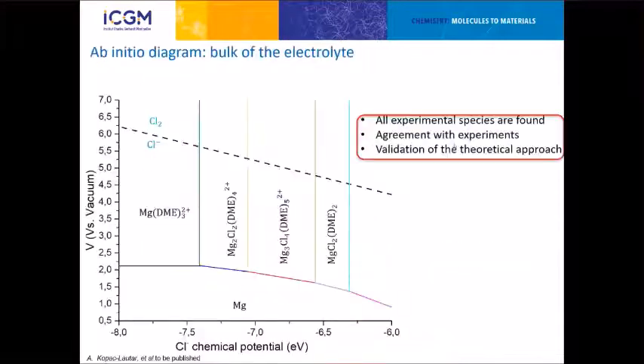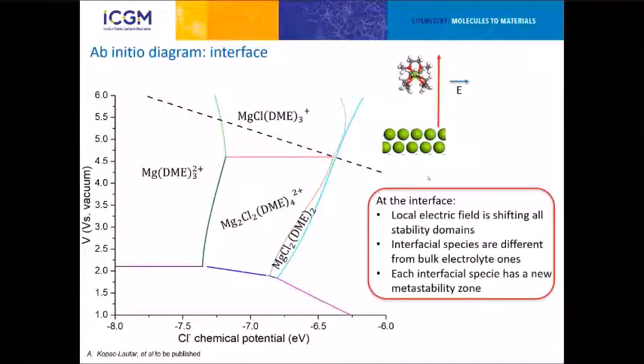So we did it, and mostly we just find the experimental observation with all the different magnesium chloride compounds, more or less complex, that are formed. So we are happy, we can find experiments, but the problem is that's the bulk electrolyte diagram. But the bulk electrolyte diagram is not really interesting to understand the electrochemistry, because in fact what you need is what is happening on the surface. So we need to really build the surface Pourbaix diagram. And in this case, we see that the diagram is really changed because of the very strong electric field at the interface. And in this case, the active species at the interface are not the ones of the bulk.